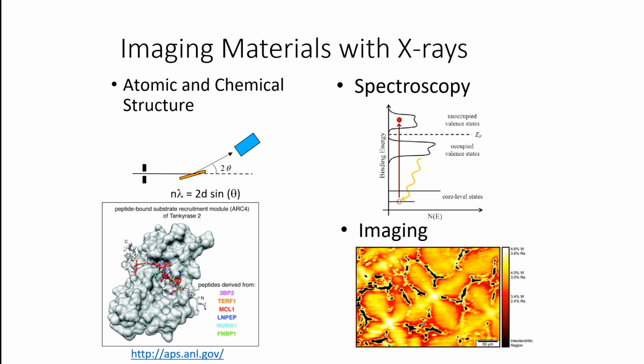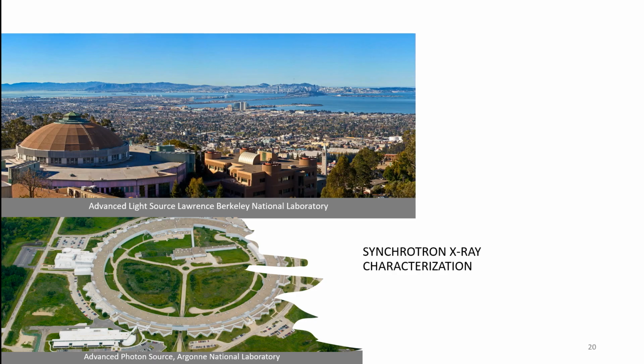And the other thing you can also use X-rays for is direct imaging, where you take thin slices of your material and then you shoot X-rays through them. This was some work I did during my PhD on some nickel-based superalloys for turbine engines. All right, so these are the two main sources that we use. We use the Advanced Photon Source outside of Chicago. We use the hard X-rays there for diffraction. And we go up to the Advanced Light Source, and we use the soft X-rays there for spectroscopy.